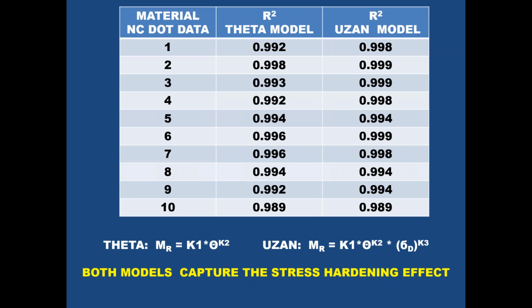There are several models around. This is the K theta to the N model that I prefer. This is the Uzan model, another popular model, which takes into account theta as well as the deviator stress. And this is some data from one of Errol's studies for the North Carolina DOT, where he had the data and we pulled this together. Notice these R-squared values for this model versus that model. Basically, they both capture the effect you're looking for. Okay, higher stress state, higher modulus, which is what we're all after.